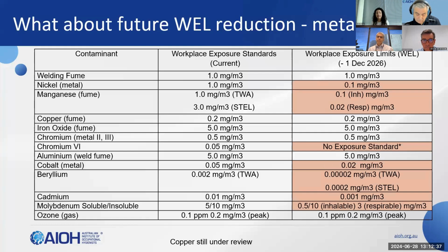So for example, manganese is actually changing to have an exposure standard for inhalable and respirable. So that is different. And you can see also, there's one further down as well that is very similar with that. Also importantly with this, we've got chromium-6. So there you can see that we've listed no exposure standard, and that's because chromium-6 is defined as a non-threshold genotoxic carcinogen. It's a bit of a mouthful. We'll probably all get used to this language pretty soon. And they don't have exposure standards set for them.